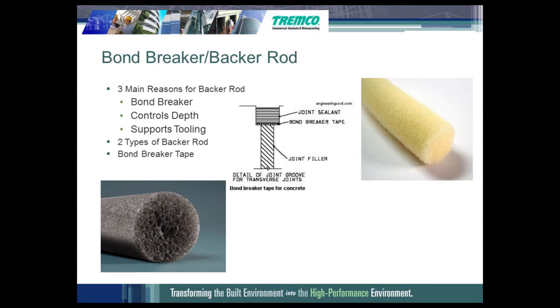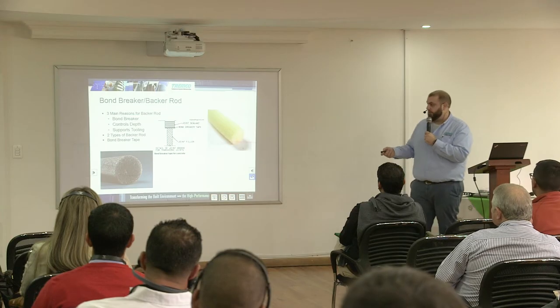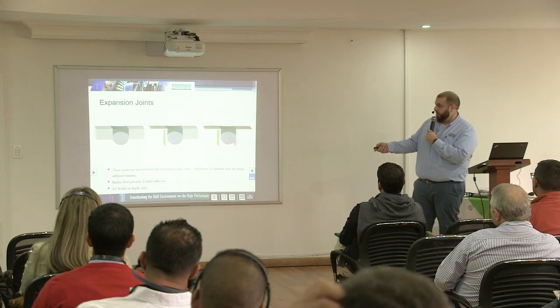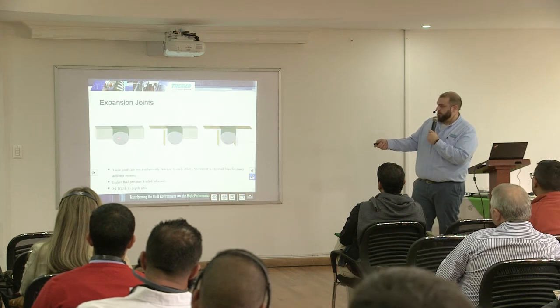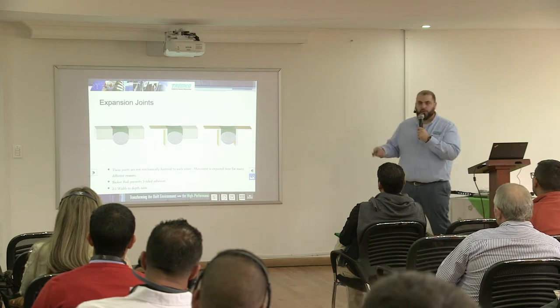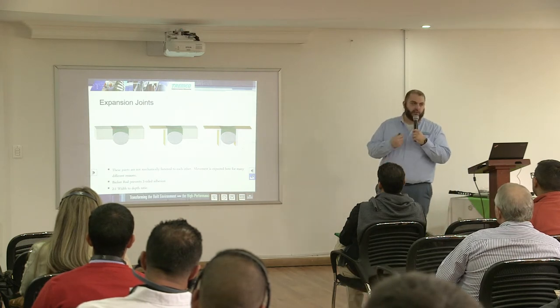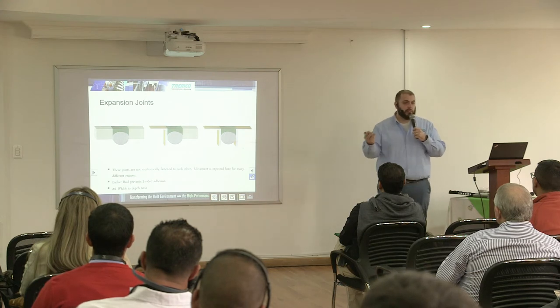Backer rod or bond breaker tape is a very important part of sealant use. There's 3 main reasons for the backer rod. The first is it's a bond breaker. If we don't have a bond breaker, something preventing three-sided adhesion, what's going to happen is, I'll go back real quick, if there was something underneath here that the sealant was bonded to, and the sealant was bonded here and here, when you saw movement, you would see tearing. You would see the sealant ripping. Or you could even see the sealant bonding so well to the substrate that you rip the substrate apart.